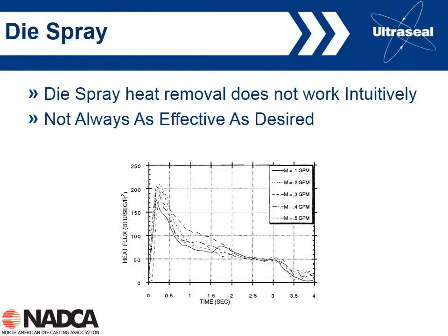So if we go from 0.1 to 0.2, which is a solid curve, up to one of these dotted curves, we get a slight increase in heat extraction rate. I should say this is obviously with the experimental conditions used here. The flow rates in your die might be different. But as in the test done here, as we go from 0.2 to 0.5, we essentially get no more heat extraction. It's not helping. We're just basically wasting our time.